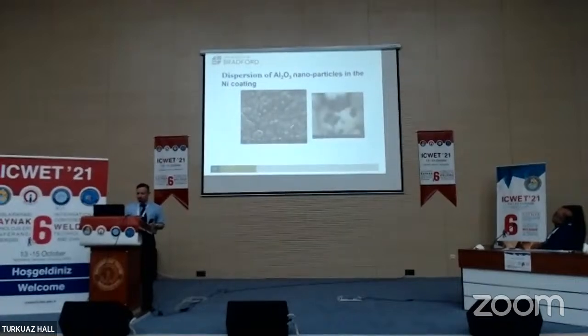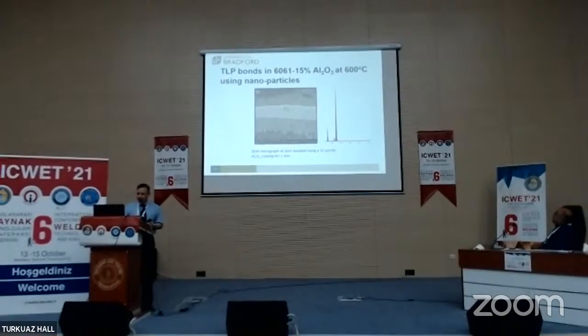So this is a higher resolution imaging of those particles, and you can see the nickel grains here, and the dark dots are the alumina ceramic particles. And this is a better micrograph here of the two combinations. The light regions being the nickel grains and the darker regions being the ceramic particles. And again, here on a high resolution SEM, scanning electron microscope, you can also see some of these particles present in the middle, and our analysis shows you the presence of alumina with a very high aluminium peak.